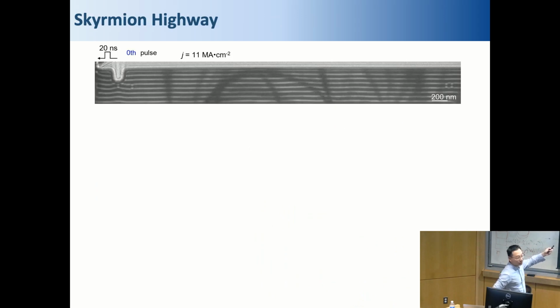There's a notch here, and this notch could help facilitate a skyrmion. But these lengths are helical lengths. So by special design of the notch, we can place a skyrmion in between neighboring helical lengths. And these helical lengths provide the geometrical constraint in the transverse direction. Maybe I should show that again. You see that this skyrmion is generated by the notch, and then it keeps moving.